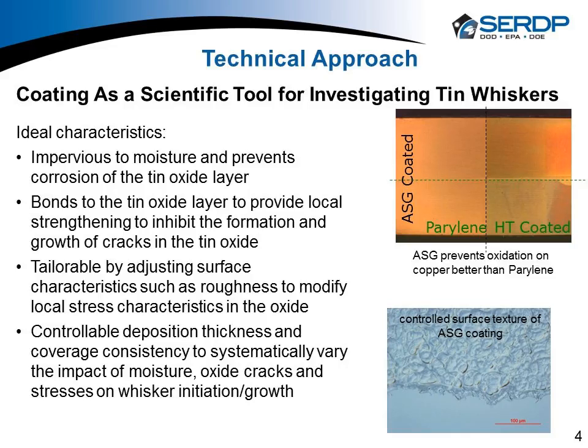And SERDP has a couple other projects going right now with Dr. Steph Meshner and Dr. Polina Signovsky looking at corrosion. And they've made some really neat discoveries and findings with their results showing that moisture and whiskers, there is a relationship there. So any coating that's going to impact whiskers has to deal with corrosion. A coating ideally would bond to the outside layer of tin in the tin oxide. Being bonded would change some things around, especially having a whisker initiate and form.